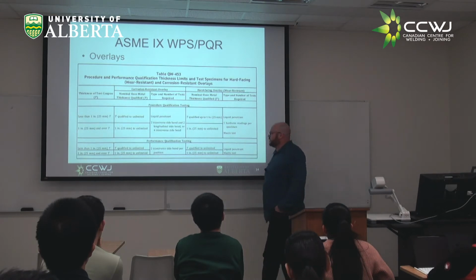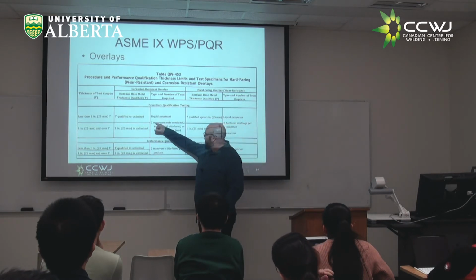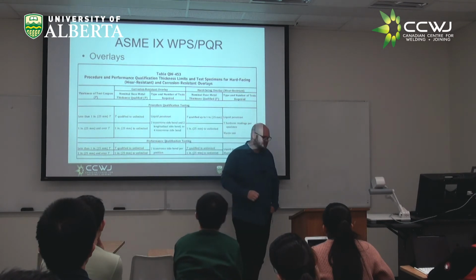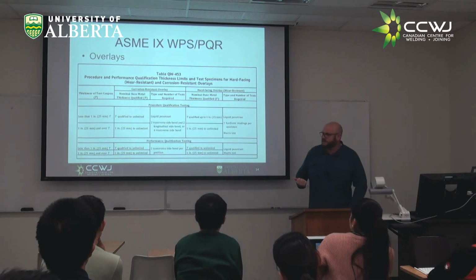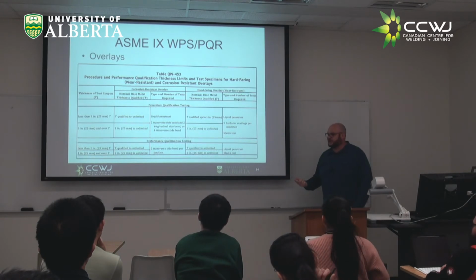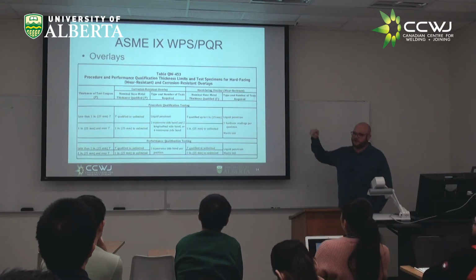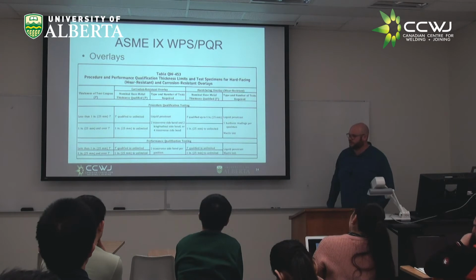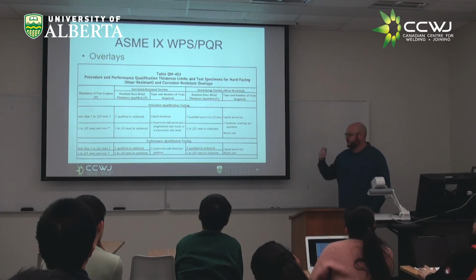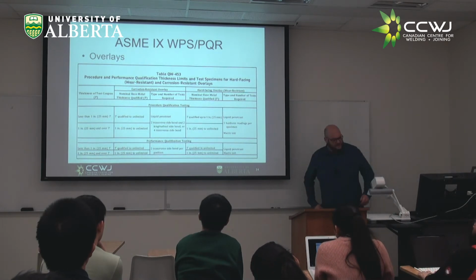to go through. The only thing that isn't listed on here, because I sort of cut it off, was for corrosion resistant overlays, if you specify a chemistry range, either by design or on the WPS, then as part of your PQR, you need to actually measure the chemistry of your overlay to ensure you're not getting dilution and you have sufficient corrosion-resistant properties.